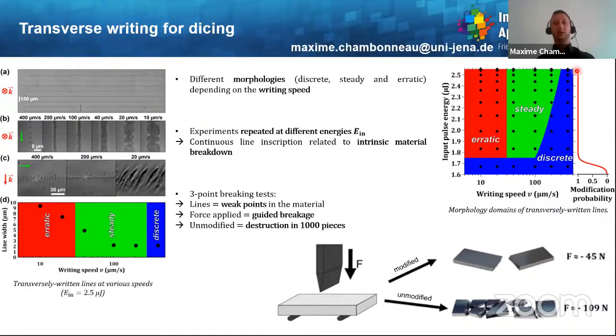So the idea here is to inscribe lines transversely inside wafers and then apply a pressure to the wafer. And one can see, as illustrated here on the figure at the bottom, that the transversely written lines can act as weak points inside the material. And when a force is applied, the breakage, the cleaving of the wafer is guided. In comparison, when the wafer is not modified, if you apply some pressure on the wafer, then it is destroyed in 1,000 pieces.